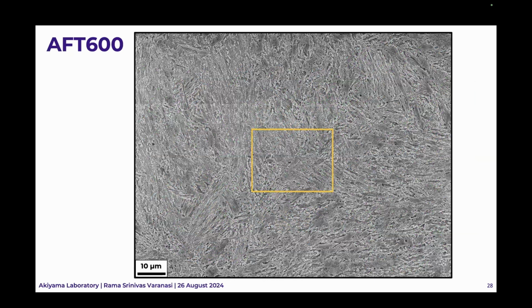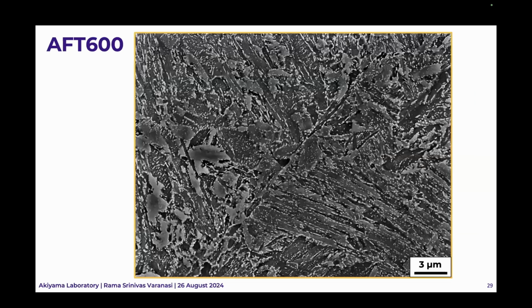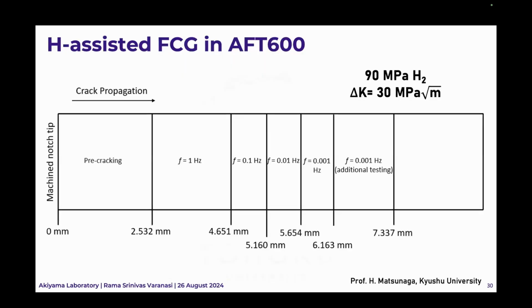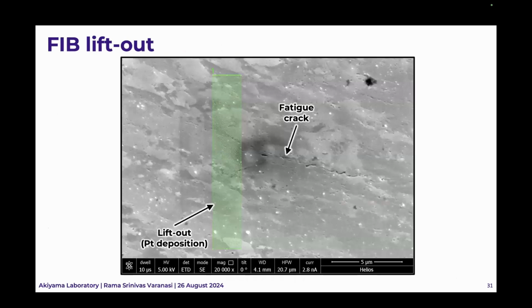However, what was very interesting for us in Ausformed 600 material is this is a prior austenite grain boundary. But now when we look at the carbide precipitation along this prior austenite grain boundary, the coverage is much lower. Again, and now why is this important? We look at this same material, but now the frequency is about 10 to the power minus 3 hertz. And we made a TEM lift-out at the edge of this fatigue crack so that we can capture the fatigue crack in the lamella.